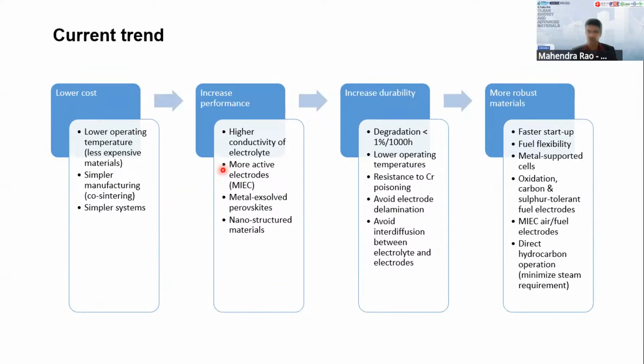So again, the performance must be shown by the high conductivity of the electrolyte, and we can use more active electrodes, MIEC electrodes, to overcome the oxidation-reduction issue and the carbon deposition issue. So there are many more issues at the electrode. And then exsolution is one of the approaches to mitigate most of the problems. And then nanostructured materials are another solution. So there are many solutions we can consider to increase the performance.